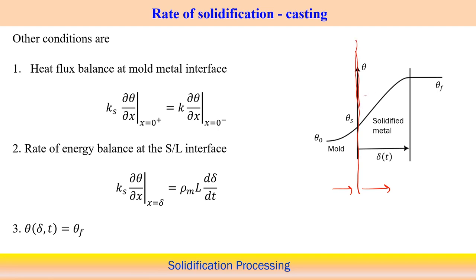So at this point 0 minus means this side, where the material is on this side, and in the other case the material is on the other side, but at the interface we can calculate the flow. In this case 0 minus is this side, that means we are taking K as the properties for the mold metal, and on the other side, 0 plus, we are considering the properties K of the solidified metal. Of course we see two different equations we have considered, x less than 0 and x greater than 0. So, as per the boundary condition, we can calculate del theta by del x depending upon the condition, the expression for x greater than 0 and for x less than 0.